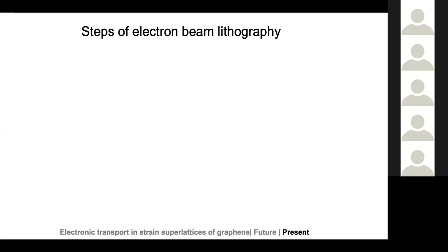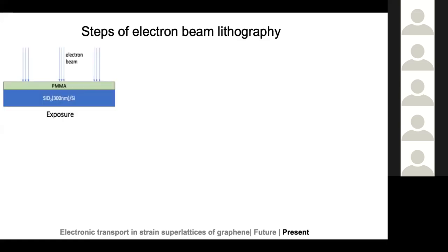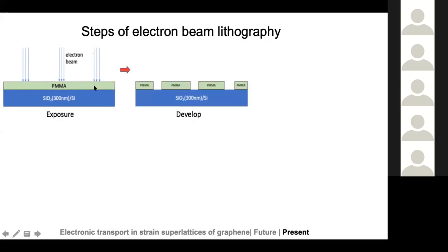If any of you have taken or plan to take the electronics optional paper, which I think is there in masters, you might learn a bit about lithography. Just to put it very briefly, in electron beam lithography, we usually coat the surface of our sample with some polymer which is sensitive to electron beam. We use polymethyl methacrylate, PMMA in short. Then we focus the electron beam onto certain regions of this device which we want to expose. These electrons will react with the PMMA of those regions and will break some of the bonds. So when you do a process called developing, which is essentially dunking your sample into a certain solution, the PMMA from these regions will dissolve. And so you'll be left with a pattern which looks something like this.